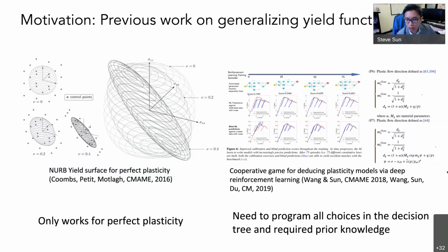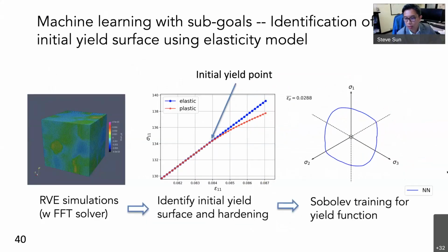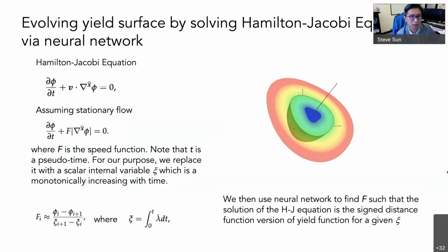The problem is that when a material shows plastic behavior, the yield surface can evolve in any arbitrary way possible. From a solid mechanics background, if we study J2 plasticity, we all know that the yield surface can enlarge in the stress space or move in the stress space. But in general, the symmetry of the yield surface can also change. It can also rotate. So one of the most generalized ways to represent that stress-strain behavior is to create a parametrization of the yield surface along with the cumulative plastic strain.